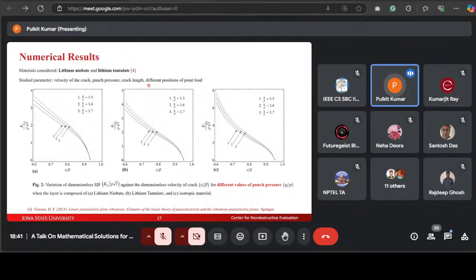So in these figures, the first one is for the lithium niobate, the second for the lithium tantalate, and the third one for the isotropic case. Curves 1, 2, 3 show the results for the increasing punch pressure. These figures indicate that the stress intensity factor for a moving crack located in the center of the layer increases as the punch pressure on the layer boundaries increases in all the cases. And you can see the stress intensity factor is higher in the isotropic material medium.